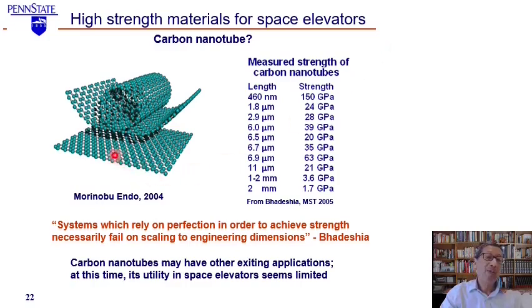A carbon nanotube is like this. If you have a sheet of atoms, all these round balls are carbon atoms, and you roll it up and you make a very tiny, teeny tube. That's a carbon nanotube. And if the carbon nanotube is very small, let's say about 460 nanometer, it has a strength of about 150 gigapascal.